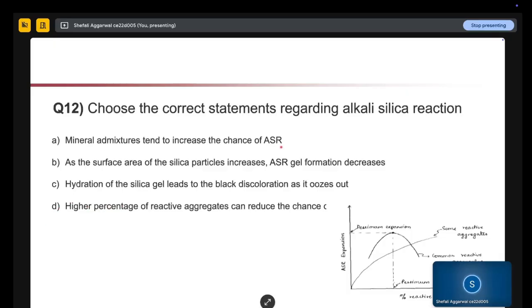Then we have mineral admixture tend to increase the chance of ASR. This is wrong. Your alkali will reduce, also your porosity will reduce in this case. Then as the surface area of silica particle increases, ASR gel formation decreases. So this is also a true statement. And then the last option is hydration of silica gel leads to the black discoloration. No, initially it will be white in color and then due to the atmospheric effect it will change to black color. So answer B and D are correct options.